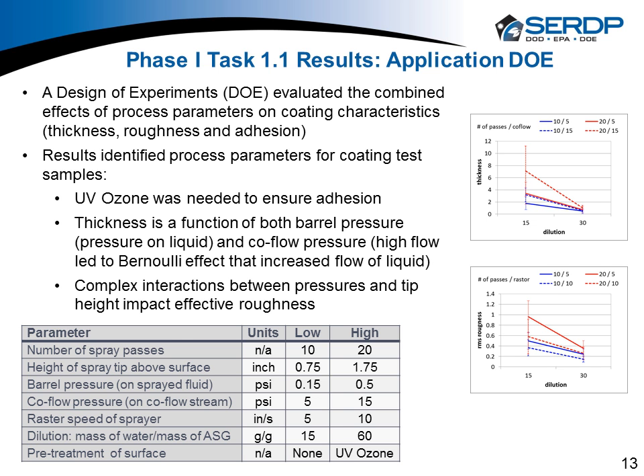One, our pretreatment. It would be nice if I didn't have to pre-treat a board, but we did show that we needed UV ozone or even some plasma, but primarily UV ozone to prepare the surfaces. We're spraying the liquid glass on a standard circuit board, so you're seeing plastics, metals, solder mask, a number of organic and inorganic things, and the UV ozone just promoted better adhesion. We also learned that to really control our thickness, we had to watch our barrel pressure and our co-flow pressure. And we found a number of interactions we had to make sure we controlled as we sprayed.